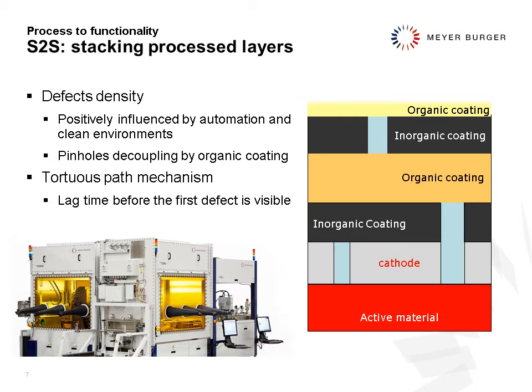So what we do, or has been done for many decades, is to decouple it by using an organic coating. So we use what is called the tortuous path. So water comes from a pinhole, whatever it is. It will have to diffuse through the organic. So diffusing, and then it will eventually have enough partial pressure at the location of a second pinhole to penetrate again. Pinholes anyway are filters. It requires a certain difference in partial pressure of water to have water coming through, and every time you pass through pinholes, the water flow is very, very much decreased.